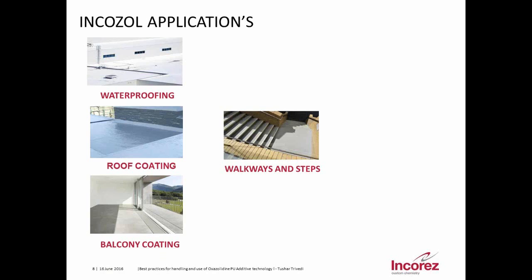Well, as I mentioned, these coatings, particularly one-component PU coatings, are high build coatings. By incorporating oxazolidine you prevent the generation of carbon dioxide, and also you get a very good defect-free film. Also, by incorporation of oxazolidine and due to the cross-linking of INCOZOL 4 and EH, you achieve very good and excellent chemical resistance and also very good tensile properties.